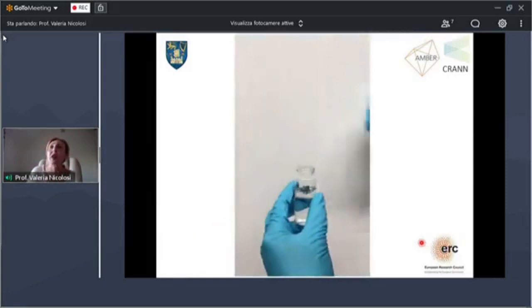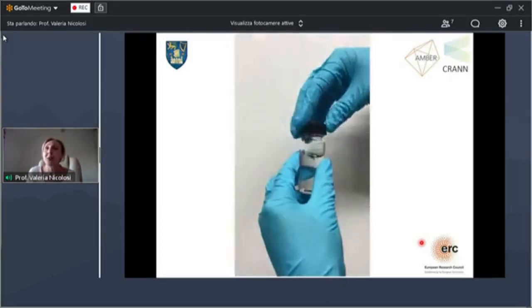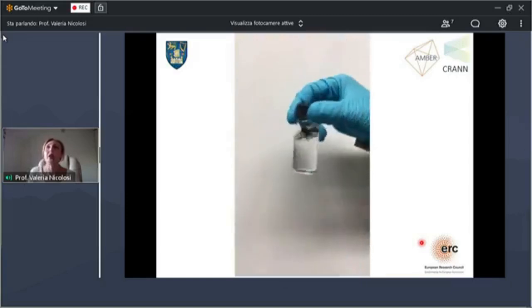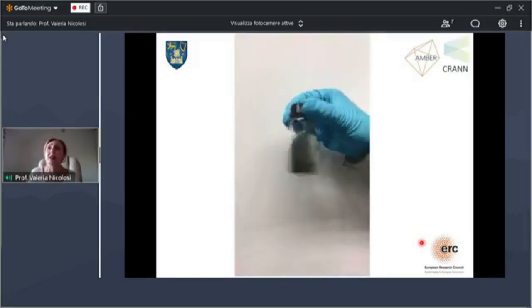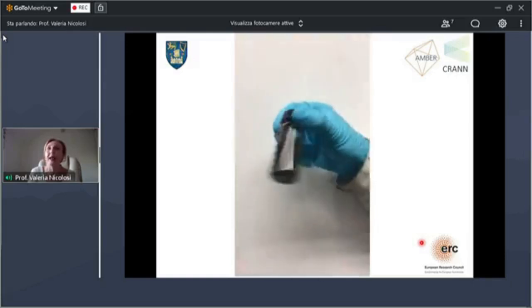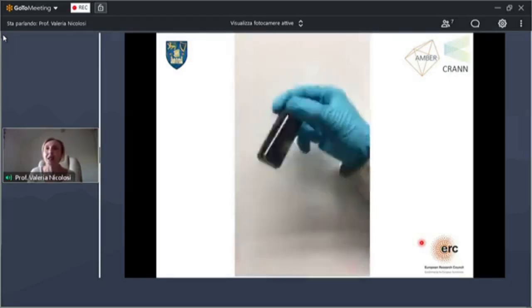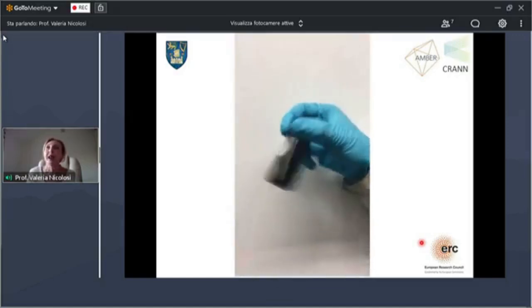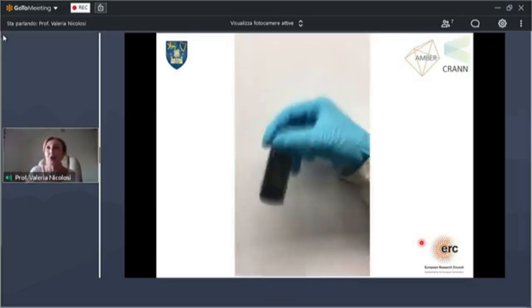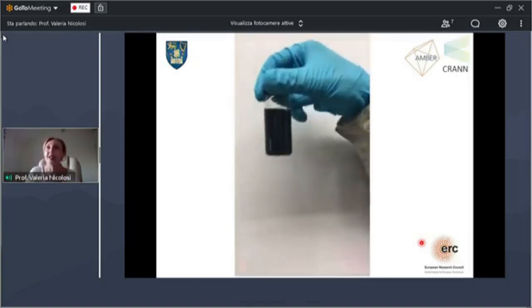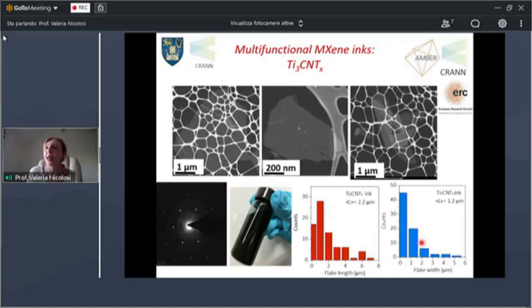Once we do that, we do conventional exfoliation. And the beauty of that is that you can also do it in water, not necessarily in very complicated organic solvents. This is how, for example, we achieve the formation of very nice dispersions that are extremely stable, and we can use simply as inks, as I will show you later. So a little handshake, and here you have a very nice and stable ink. These inks are indeed made of 2D materials that are extremely thin, 1 layer only in thickness, and very, very nice and ordered and pure.